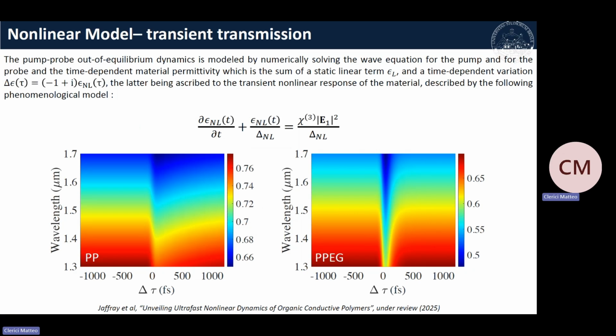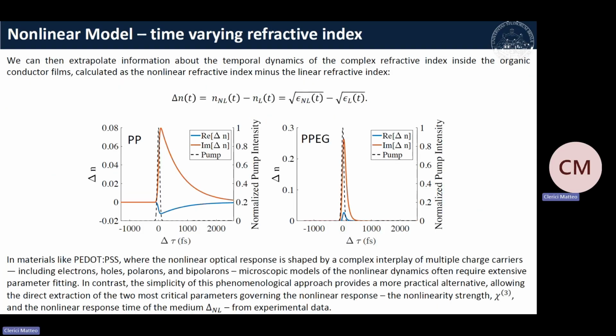We model our system to quantify the nonlinearity. Now, because PEDOT:PSS and doped PEDOT:PSS is a very complicated compound, we have electrons, holes, polarons, bipolarons. We kind of summed up everything into an effective Chi3. And what we found is that we actually have, over time, a refractive index modulation that impacts both the real and the imaginary part, as big as 0.1 for the imaginary part and of the order of 10 to the minus 2 for the real part, over the peak on the overlap of the pump and the probe.